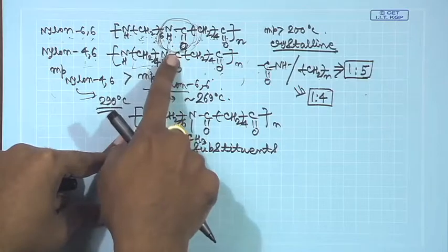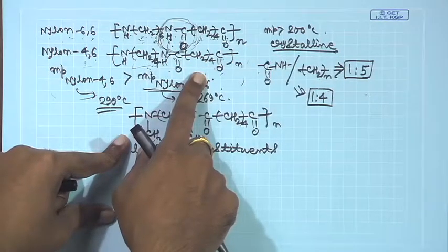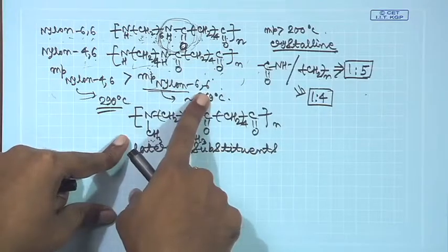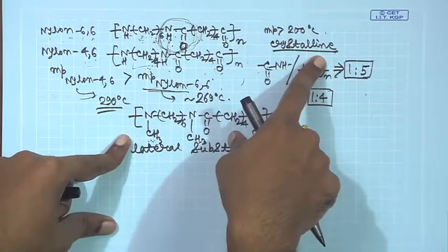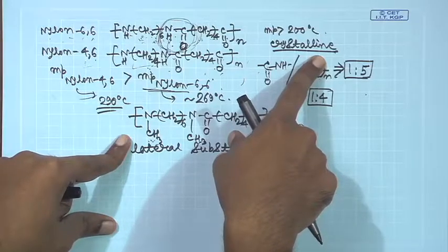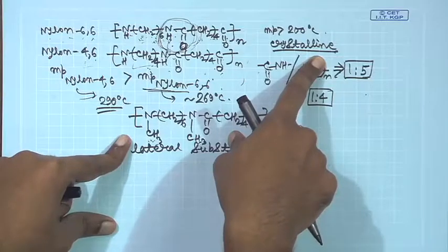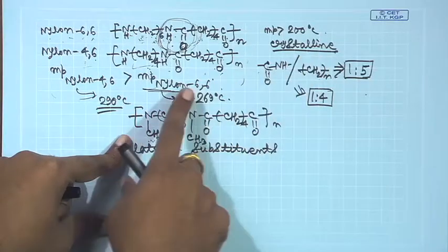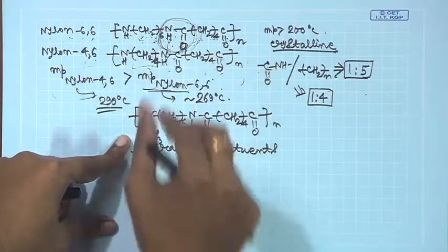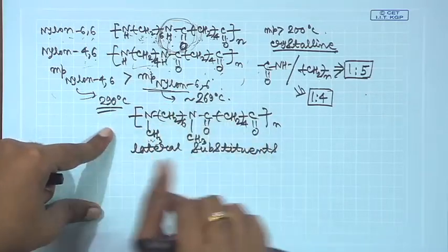So, hydrogen bonding is at the heart of crystallinity of these materials, it is at the heart of the high melting point of these materials, and this is also the reason why the nylons are typically very stiff materials. You will see that for fiber applications you can use nylons, nylon ropes, and so forth. You get those kinds of stiff materials because you have aligned hydrogen bonding interactions. But if you now destroy this hydrogen bonding interaction, then you will also destroy crystallinity.